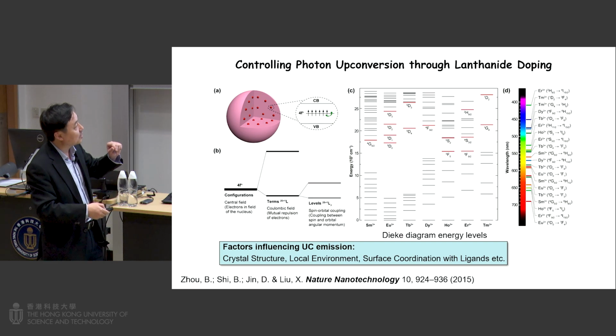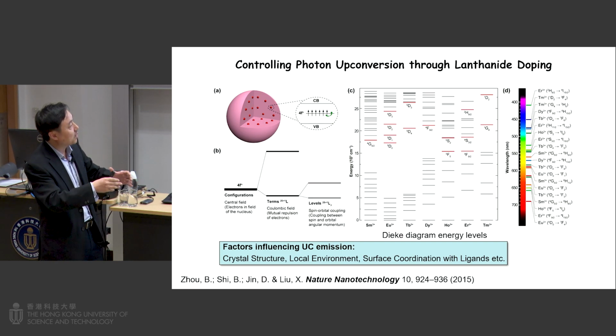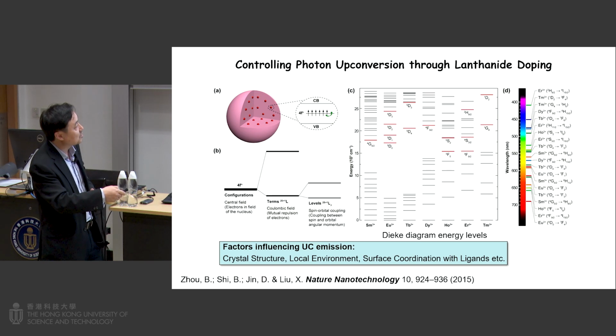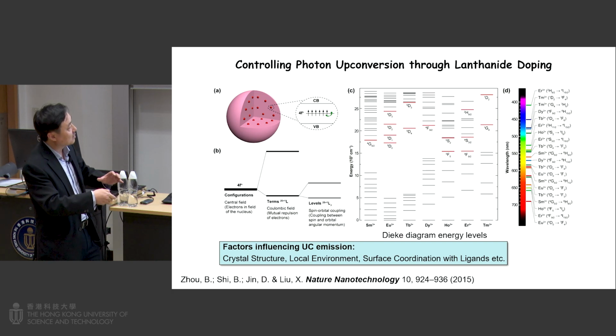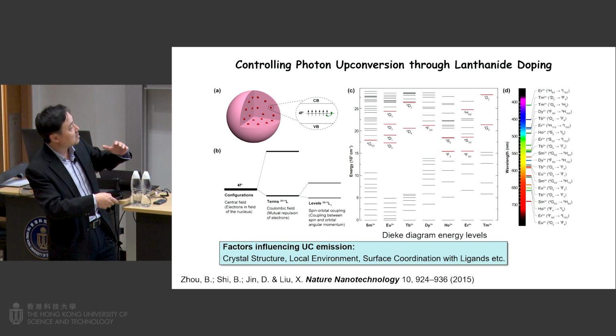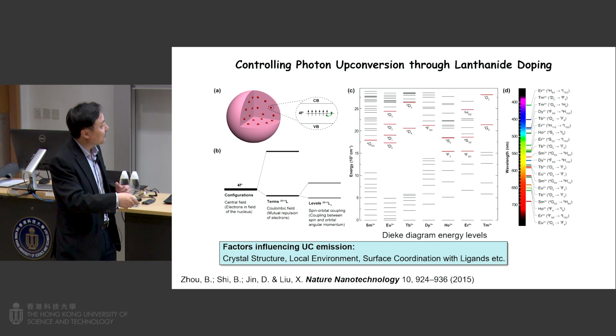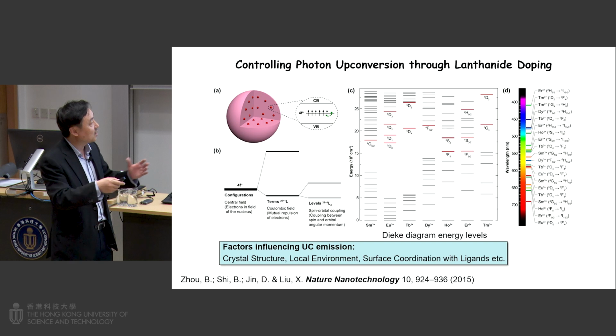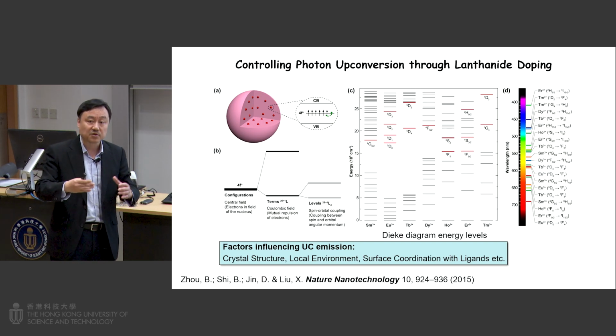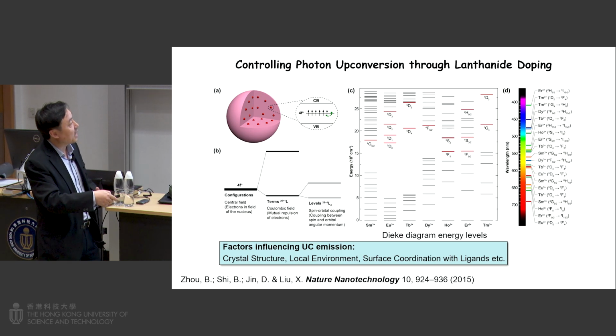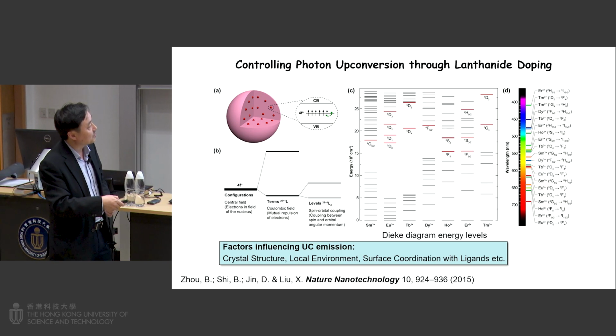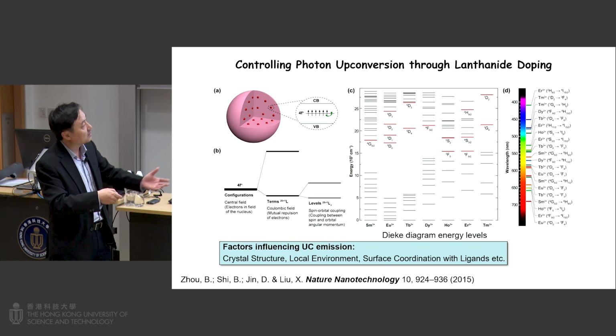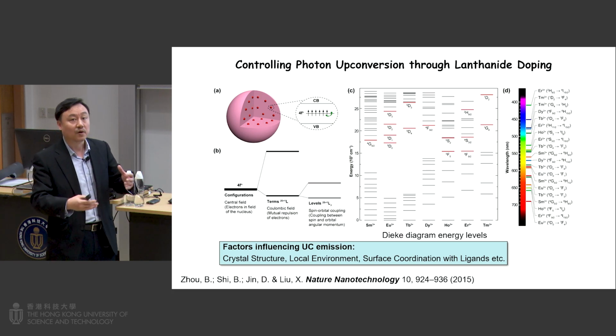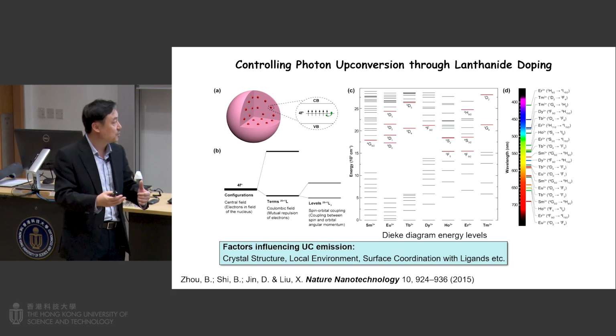We can control the colors by controlling the energy transfer, the transitions between energy levels. For lanthanide ions, the number of energy level transitions is enormous. For example, europium has more than 3,000 energy levels, so for calculations it becomes very challenging. But luckily, from many experimental results, we can now be pretty confident in controlling the emission colors by adding different dopants or by playing with the dopant concentrations.